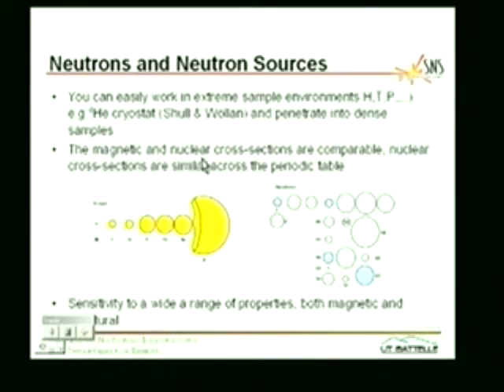The cross sections, which determine the scattering, how the scattering intensity relates to things like atomic positions, are first off, magnetic and nuclear cross sections are essentially the same size, which is not the case with X-rays.